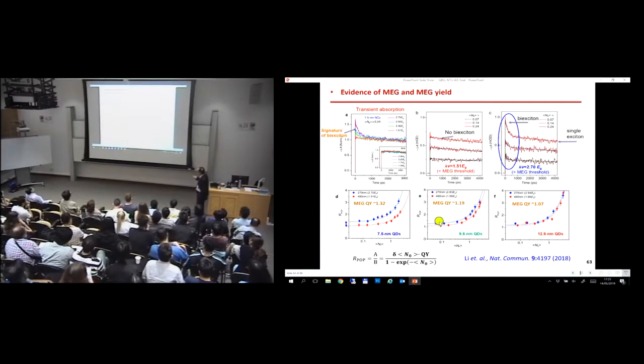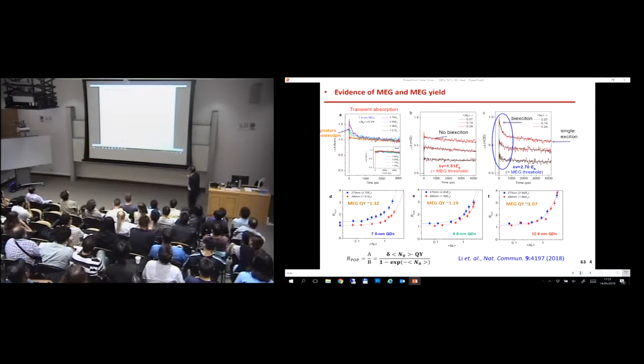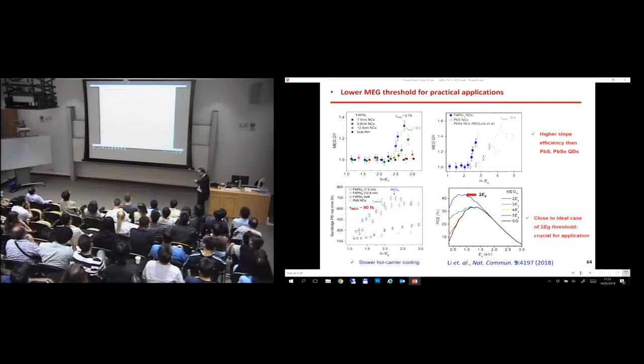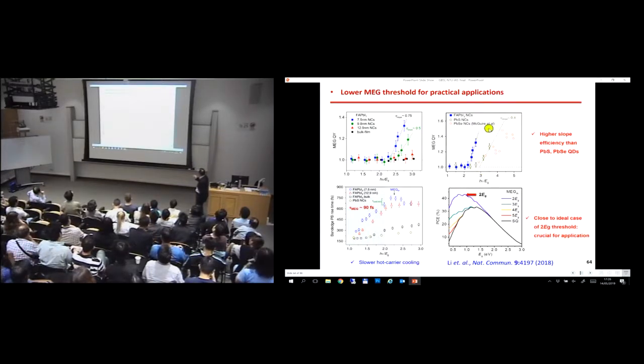As you make the particles go to larger particles, this MEG quantum yield actually decreases. Now, a key litmus test is that of the threshold. I draw your attention to the open red dots and the black dots. Those are the lead sulfide and the lead selenide nanocrystals. One is data that we reproduced from the literature, the other is data that we collected using our experiment.